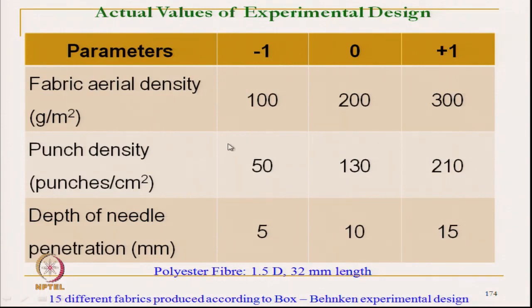So, in the first study, we used polyester staple fiber of 1.5 denier with 32 millimeter length. This polyester fiber is used to produce nonwoven fabric, with different mass per unit area, that is 100, 200, 300 GSM. We have used a Box-Behnken